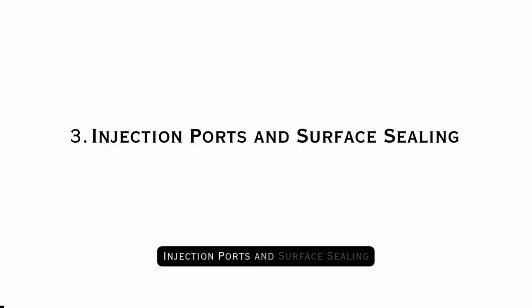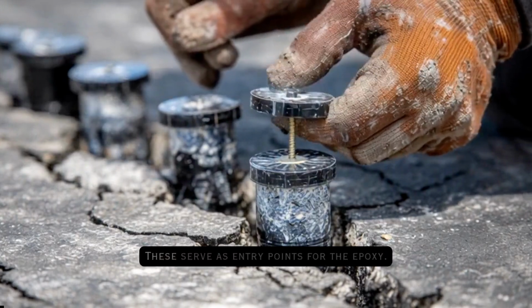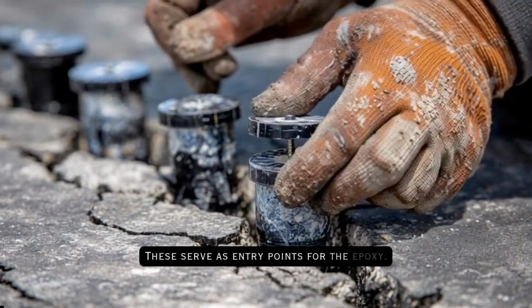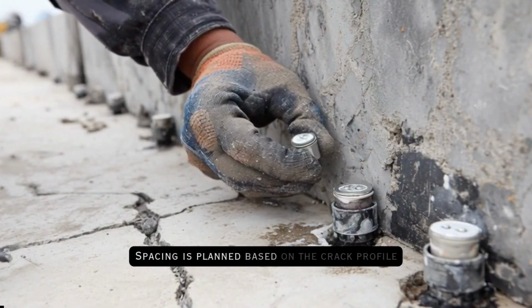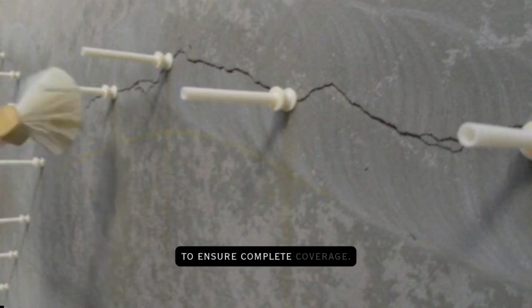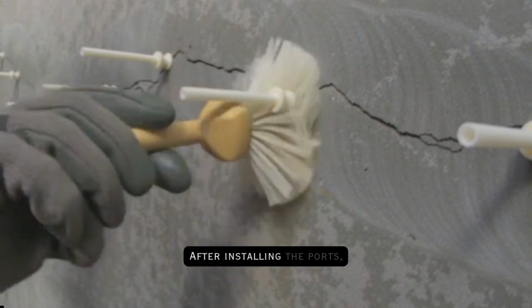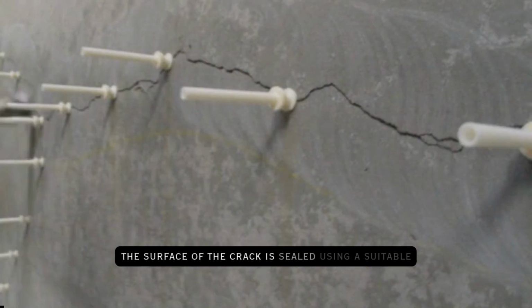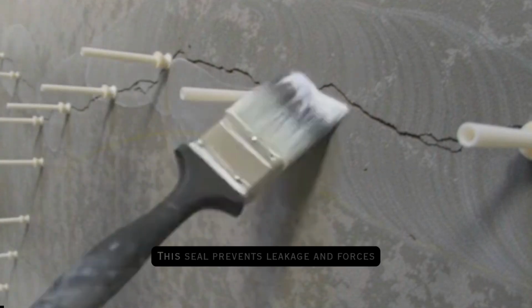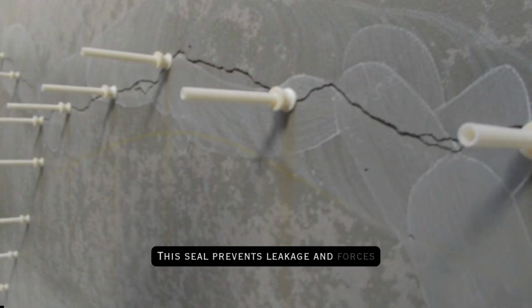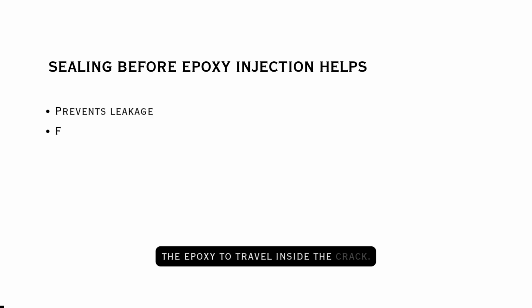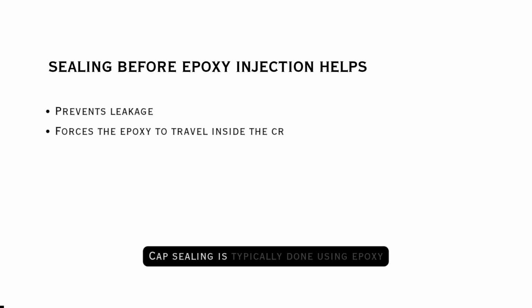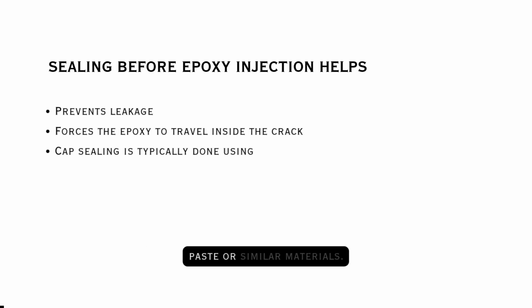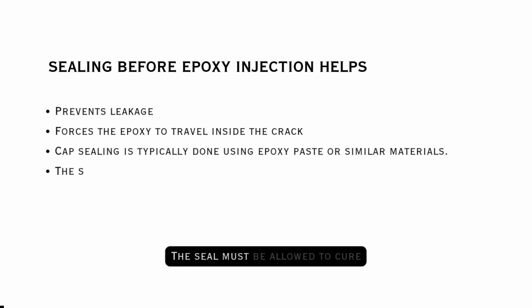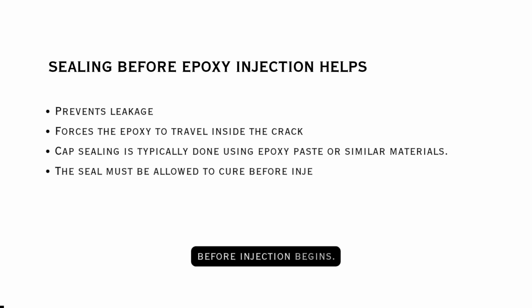3. Injection ports and surface sealing. Injection ports are installed along the crack. These serve as entry points for the epoxy. Spacing is planned based on the crack profile to ensure complete coverage. After installing the ports, the surface of the crack is sealed using a suitable sealing material. This seal prevents leakage and forces the epoxy to travel inside the crack. Cap sealing is typically done using epoxy paste or similar materials. The seal must be allowed to cure before injection begins.